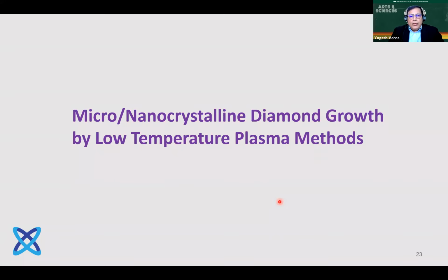Okay, so now we are going to make a transition. So the two examples I gave you so far were where we have grown a single crystal diamond on top of an existing, so to speak, seed crystal. But we can also grow microcrystalline films or polycrystalline films, and into the extreme, we can grow a very fine-grained nanocrystalline film where the grain size is billionths of a meter using the low-temperature plasma.